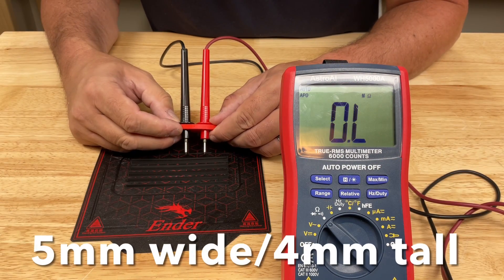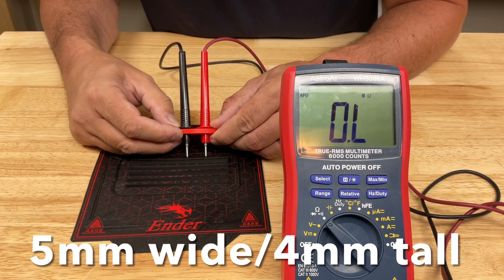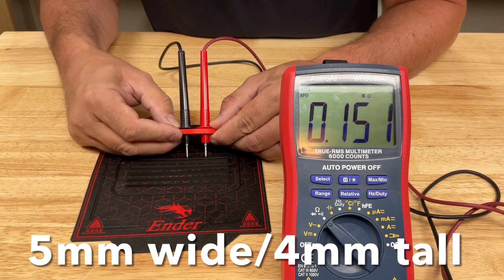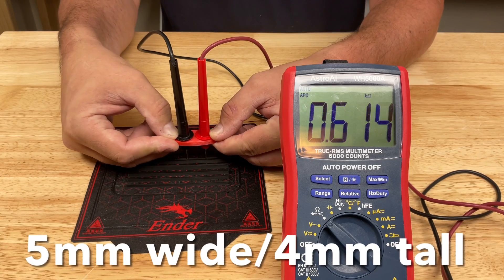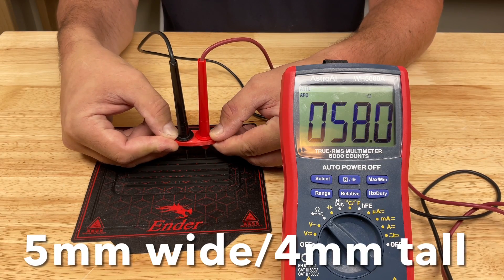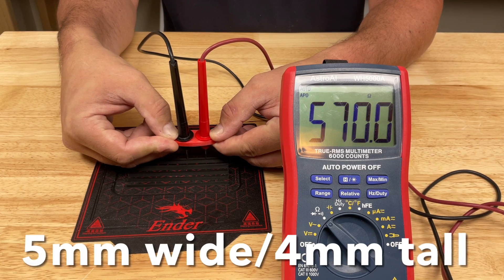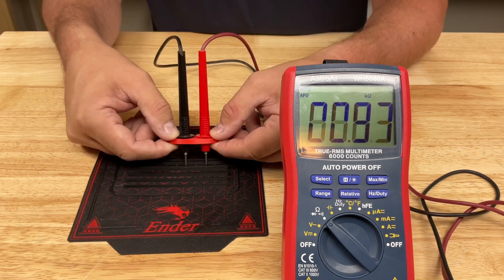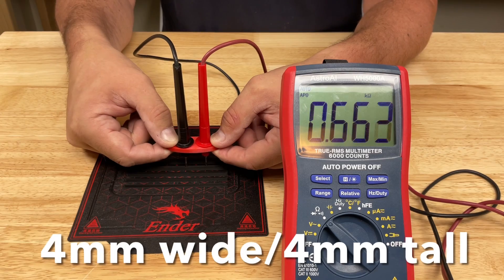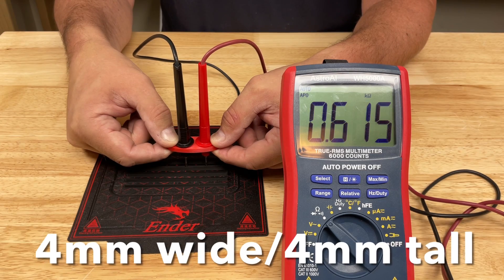I did five different prints. This one's the four millimeter tall. I did a one two three four and five so I'm testing the five millimeter wide strip by just pressing hard to get rid of contact resistance, 570 ohms.